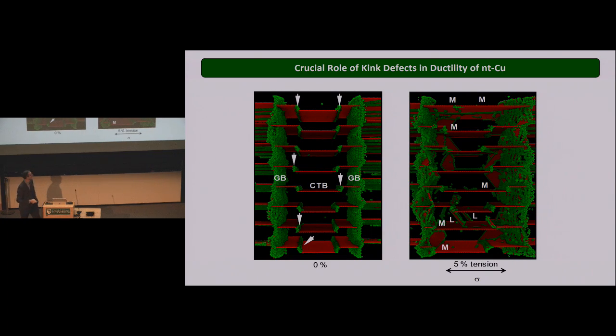And so again, to illustrate that, this is the example of the first movie where we compare before and after deformation. For instance, these have disappeared, so there's total migration of the defects. In some other location here, what's noted as L represents the formation of a Lomer lock. And the Lomer lock actually is responsible for much of the hardening in conventional metals. Again, these are things that you could not predict by assuming that the twin boundary is a perfect interface. Okay, so truly they are defective.